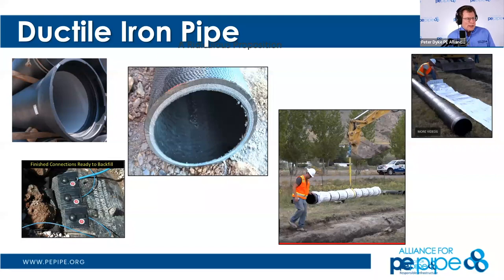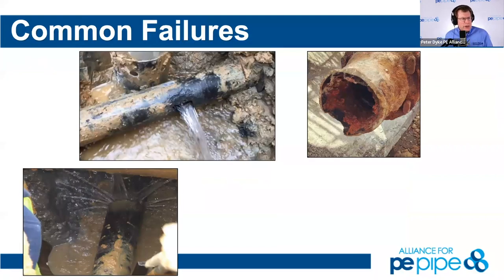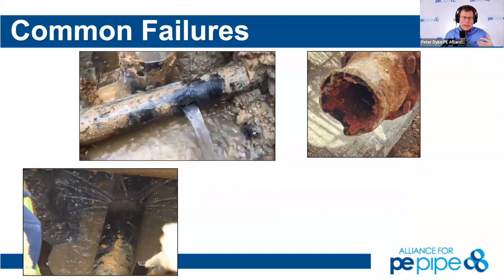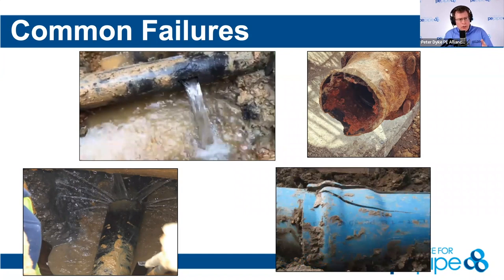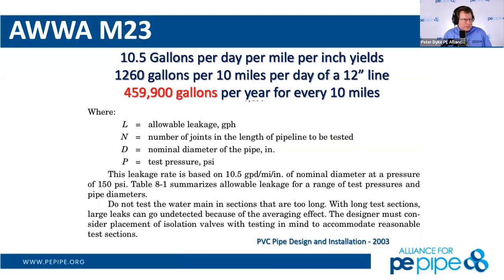So that's the product differentiation. I need to put that into a one-pager. So what kind of failures do we see with legacy systems that polyethylene has solved? We see cast iron circular breaks. That's a common way cast iron fails. Ductile iron fails with tuberculation, both inside out and outside in. And then finally, we see over-insertion with PVC and cracking of the bell and spigot with over-insertion. All right, next slide. Then we have what we call allowable leakage rates for legacy pipe systems.